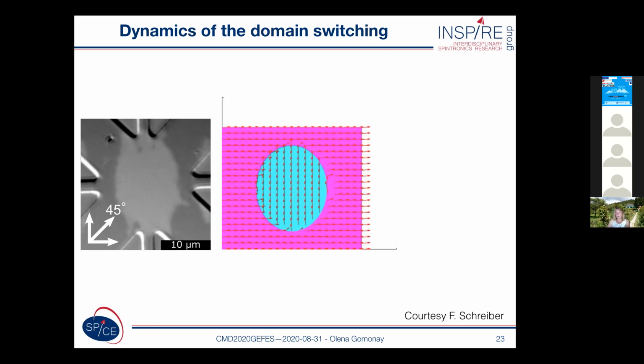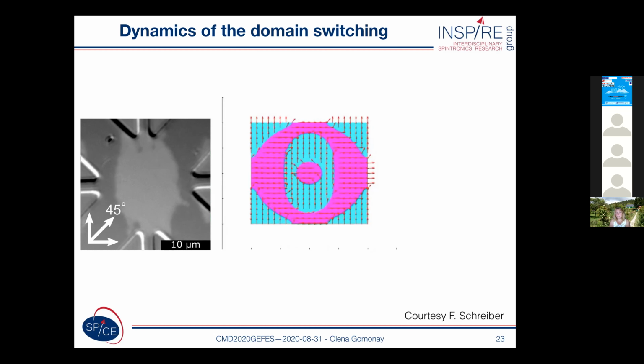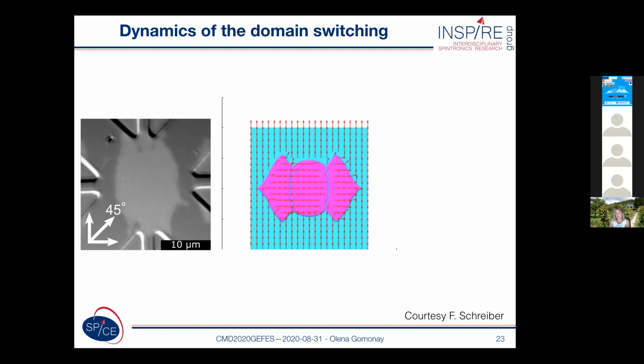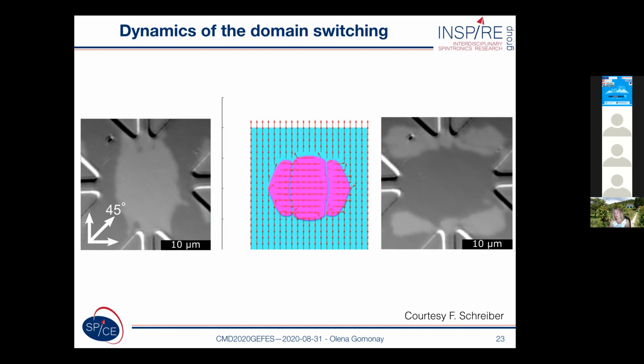So now I will show the video of how the system changes its state when you apply a strain field which is consistent with the distribution of the current induced strains. So you see that the process starts from the edges of the sample, and then the system switches 90 degrees, which is very similar to what you really see in the experiments.